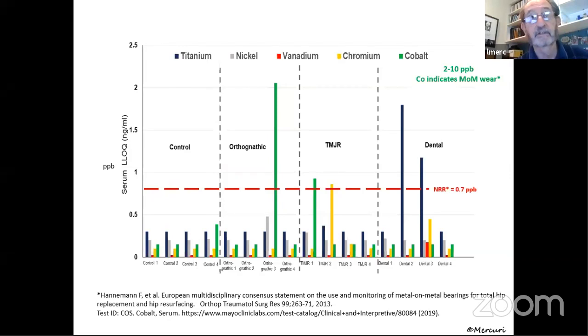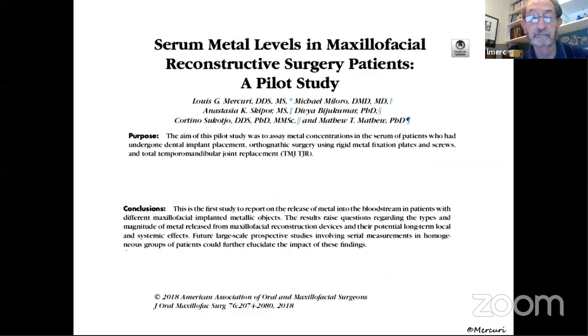There's been some nice studies done in Brazil looking at the osteoblasts around dental implants that show that what happens is the titanium ions are picked up and stored in vacuoles within the cytoplasm and really don't do anything. The problem here with cobalt is that cobalt has multiple ionic forms, some of which actually get into the nucleus of the cell. So we're real concerned about cobalt. But again, that's a whole other story which would take hours to talk about. So what we came to the conclusion with this study is that we need to study this more.